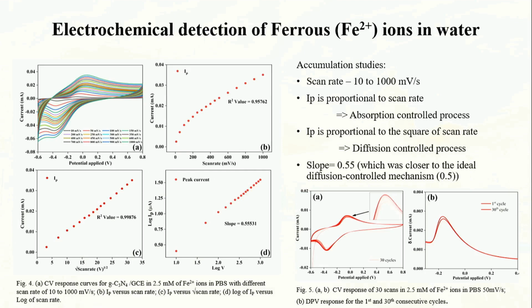Here, in the second graph and the third graph, we relate the peak current of the oxidation peak to the scan rate and the square root of the scan rate, based on the Cottrell's equation. Both of them show a linear relationship, with R square values more than 0.95 and 0.99. So we think this involves both adsorption and diffusion control processes.